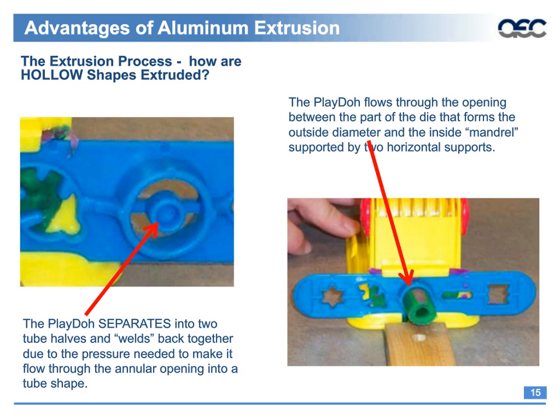This simple example of a Play-Doh machine actually shows how it happens. It's not a true seamless tube, but the material comes around an internal mandrel, which allows the material to split into two or more parts, and then so much pressure is required, and there's also some space on the backside of an actual extrusion die where some mixing occurs. But then the extrusion comes out as a tube, which doesn't have a seam. The seam is actually over a distance around the periphery of the tube.